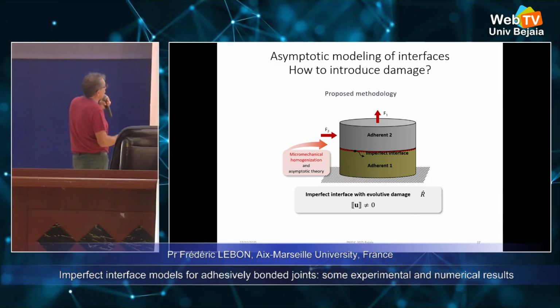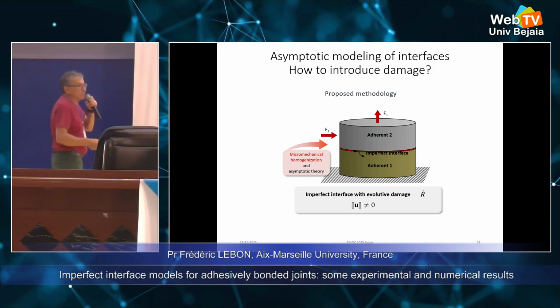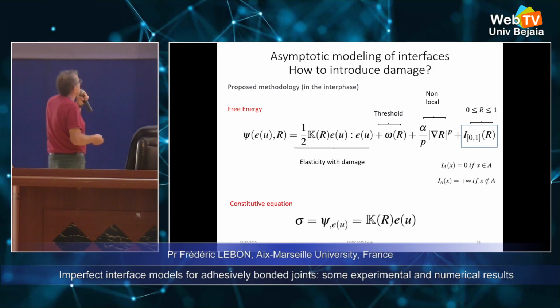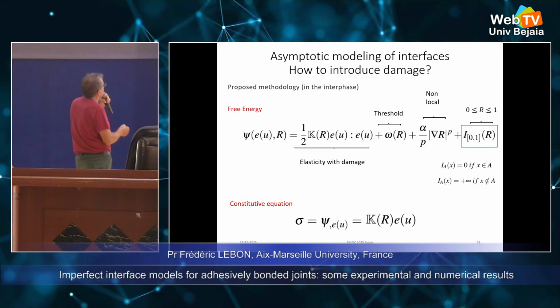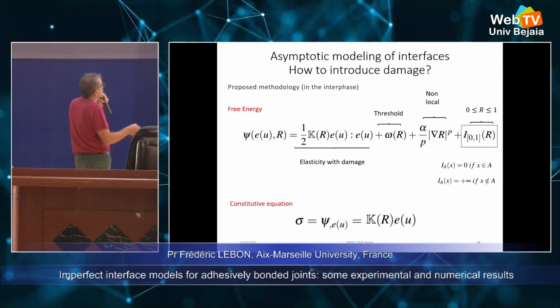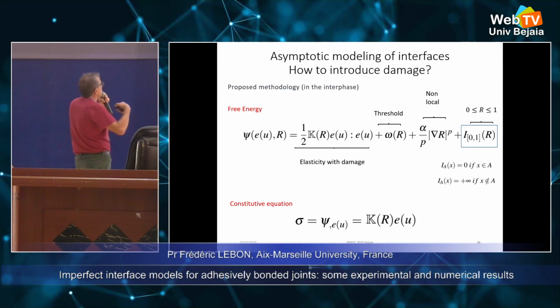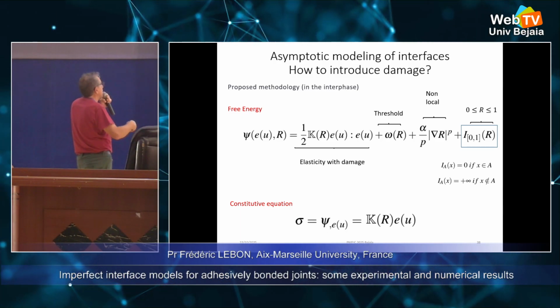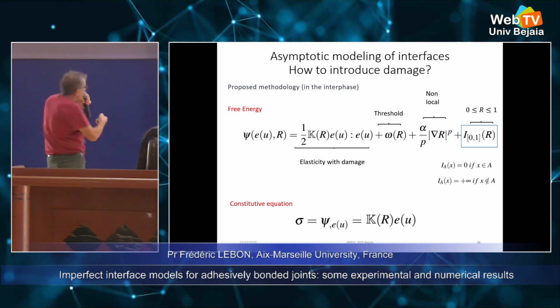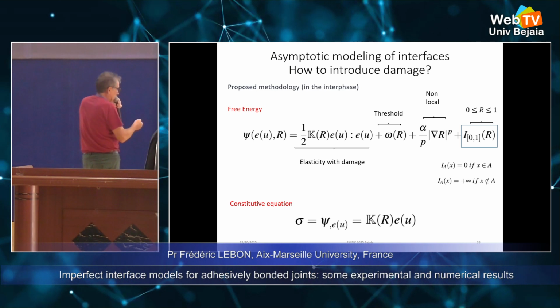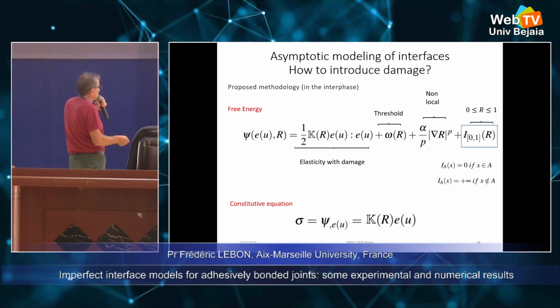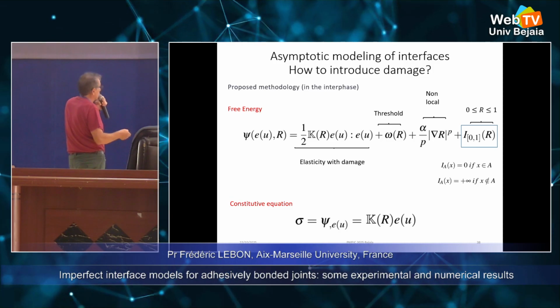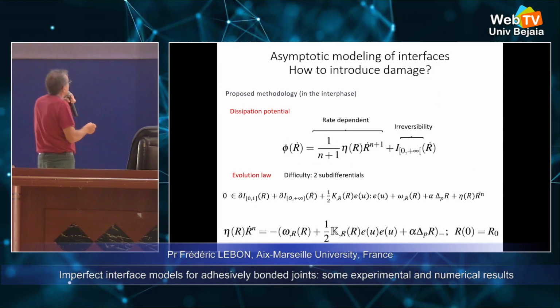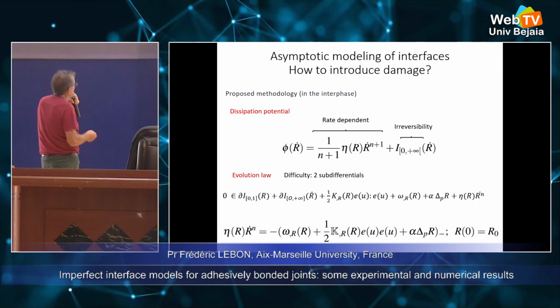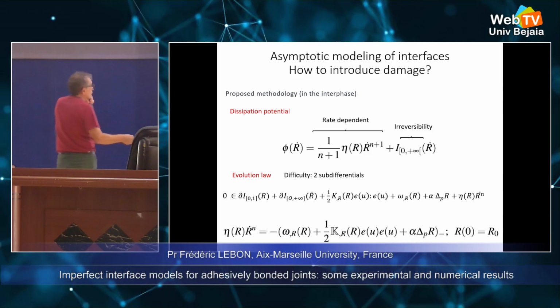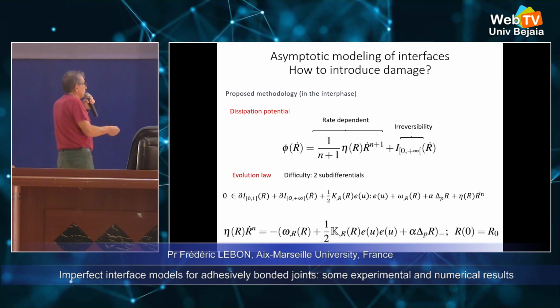And so we have to add an evolution law for the damage, because the damage depends on the loading. So there is a free energy, the classical free energy, introducing a threshold, because the damage doesn't start at the starting of the experiment. There is a threshold, and after that you obtain the classical constitutive equation, the stiffness depending on the damage parameter. We introduce a pseudo-potential of dissipation, okay, and we obtain this kind of evolution law, which is very general, and in fact the evolution of the damage depends on the energy.